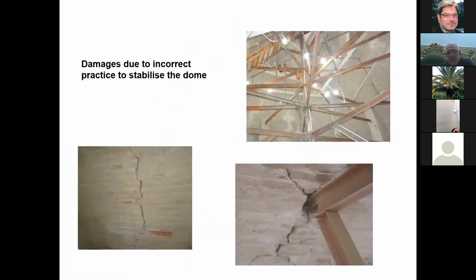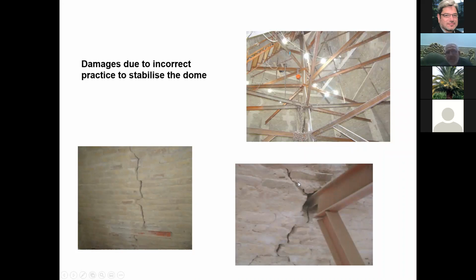In the old days, the way it was strengthened, every time they saw that there was a movement or a crack, they would build a steel frame like that to support the dome. But you can see here, this was done in the 50s, 60s, and 70s. The strengthening that was done here was actually doing more damage than supporting the dome. Because this is a rigid element, any movement here, any settlement, any movement in the dome, this is going to puncture into the body of the dome. So there was a lot of damage due to the internal system that was used at the time.